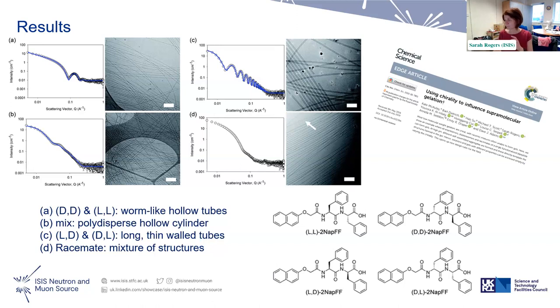So we did some microscopy, and you can kind of see that all the fibers are formed, but it was really difficult to tell if they were truly different. And then when we did the scattering, you can clearly see that the fibers formed are very different from each other. So if you have the DD and the LL, you form these more worm-like structures, sort of wrapping around each of the hollow tubes. If you have a mix, you get this polydispersity that's added in. LD and DL also give these sort of long, thin wall tubes, but they tangle around each other less. And if you have a racemate, you basically get a mixture of structures, as you can imagine. So again, from the scattering, you get a very detailed picture of why these different types of gel are forming, and it helps people design better or tailored gels for the future.